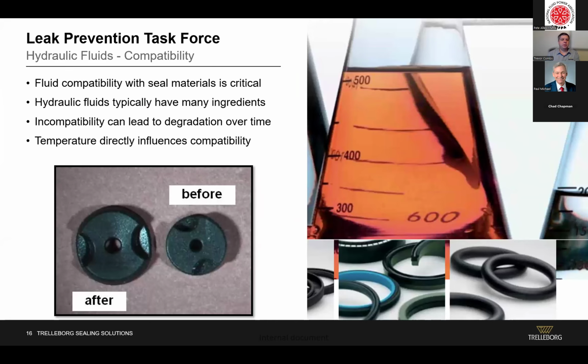So a few things to look at when you're looking at hydraulic fluids in a hydraulic cylinder is fluid compatibility. So you want to make sure that the seal materials and the hydraulic fluids are compatible. If they're not compatible, you can see swelling, you can see shrinkage. And with a lot of the fluids now, there's a lot of ingredients, a lot of additives, a lot of different things that you're not always sure how they're going to interact with the seal materials. So it's important to have some testing or some baseline understanding of how that material is going to perform with the fluid that you're using.